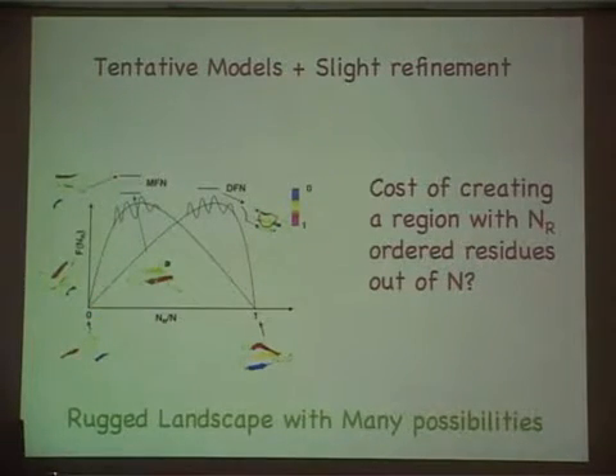So then you can imagine, because of these two opposing forces, it's likely, though not super clear, that if I plot the free energy of creating such an ordered region as a function of the fraction of residues that are in fact ordered, you would have a barrier, just like in the homogeneous nucleation theory. However, you know a priori there's a distribution of radius of gyration. I showed you that. And therefore, this landscape cannot be as nice as I've drawn it here, but it's got to have some ruggedness associated with the fact that there could be structures forming everywhere, because fluctuations within that nucleated structure with N_R residues can be very large here. I'm going to refer to this as a multiple folded nuclei model, and there are many such nuclei that you can form anywhere, in fact, in principle, as long as you don't violate topological restrictions.